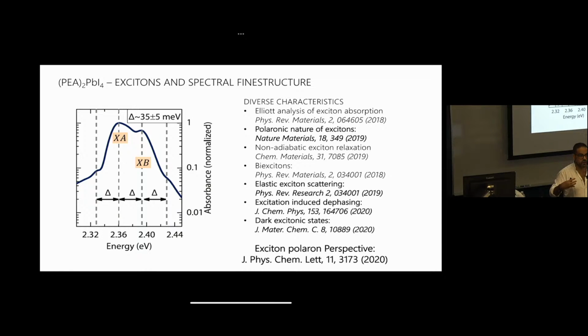The charge, because it's such an ionic and dynamic system, the photocarrier is strongly bound to the lattice via phonons, and that dressed photocarrier will have consequences, and the effects on charge transport are going to be important. These materials are known to have, although very long carrier lifetimes, relatively limited mobility, and so it has been understood that polaronic effects are important. What's a polaron? It's a charge that is very strongly coupled to the lattice. In the regime of gallium arsenide, it's through just phonons.